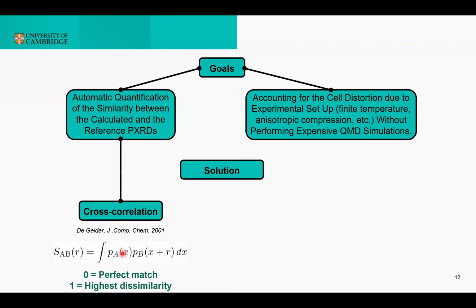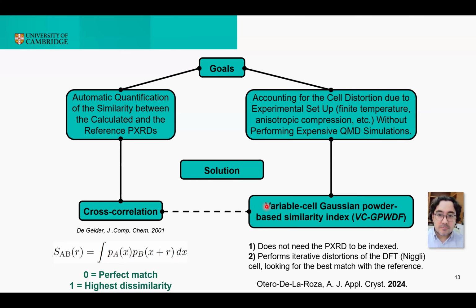The first problem can be solved quite easily by calculating a similarity index, for example, based on the cross correlation functions, like in this case. Since what we calculate in the end is actually the degree of dissimilarity between two diffractograms, the value 0 means that the two powder diffractions, or two diffractograms, are nearly identical, while one gives the highest level of dissimilarity. Solving the second point instead was very tricky.